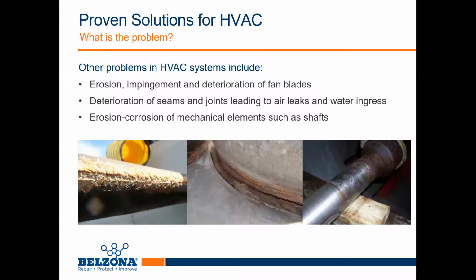Cooling tower fan blades usually suffer from erosion on the leading edge, as well as cracks and flaking on the edges, reducing the overall efficiency of the cooling system, ultimately leading to failure. Ductwork, whether through active operation or natural convection, can develop rust due to water content in the air. Condensation weakens and corrodes the metal of these ducts, which can lead to a breakdown in the structure and subsequent structural and operational failure. Rust buildup can also lead to secondary problems such as mold and the introduction of harmful particulates into the ventilation system, providing health issues for the occupants.